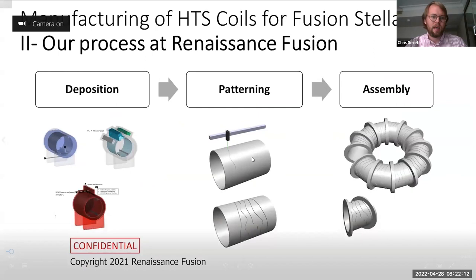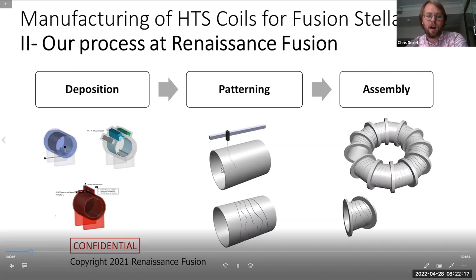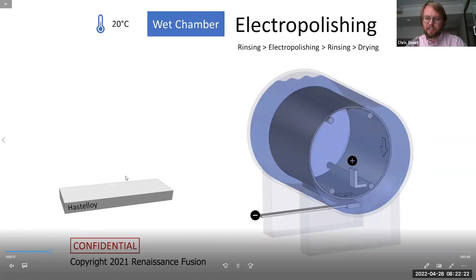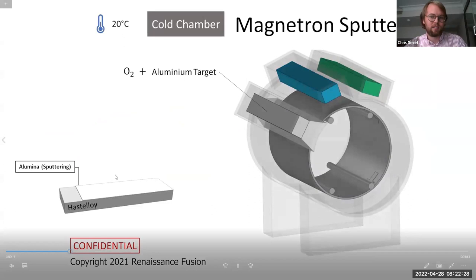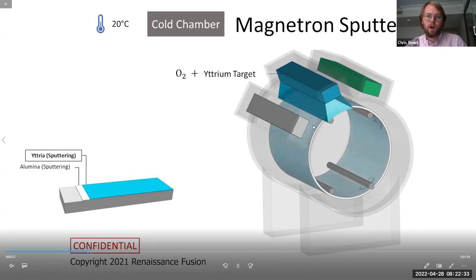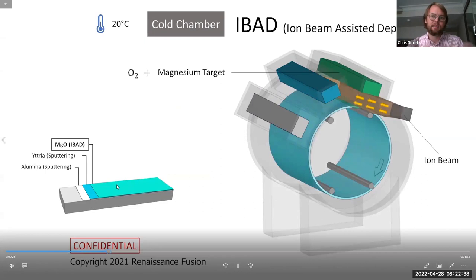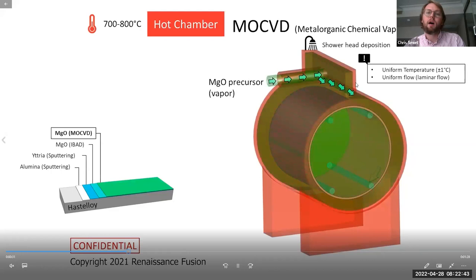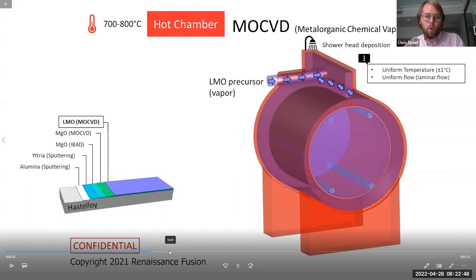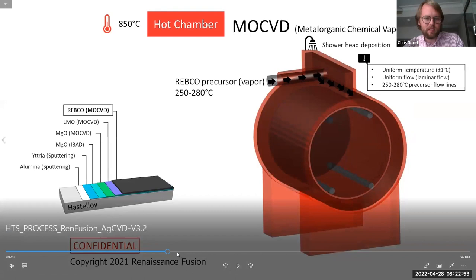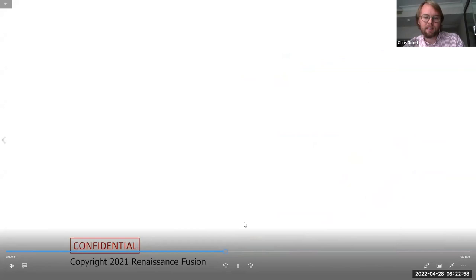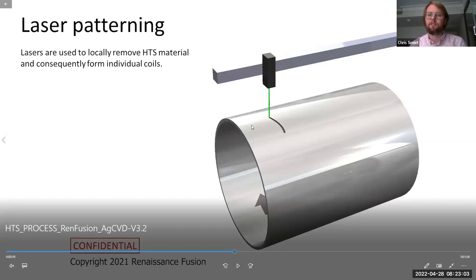And so we want to deposit the superconductor directly on cylinders, on structural materials of the vacuum vessel, because the deposition process, you can deposit superconductor on anything. It doesn't need to be in that tape form. So on the entire cylindrical surface, we plan to deposit the same stack and get the same quality of superconductor. But then deposit the superconductor on a wide area. So having that deposited, we can define channels inside of the superconducting layer. And these channels will then channel the supercurrent.